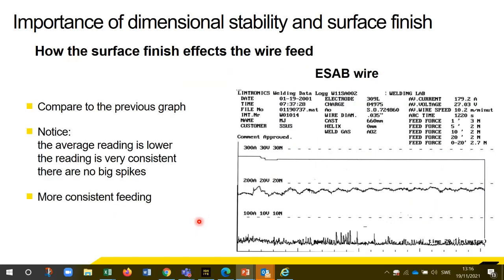If you compare it to this graph, which is an ESAB wire, exactly the same parameters. It's a 20-minute feed test, and it's what we do for every batch. The 20-minute feed test, you can see the whole power usage is lower. The average is certainly lower than previous, and the spikes are not so high. It's more constant, it's more even. That means you're going to get a better, more consistent feeding. This helps.